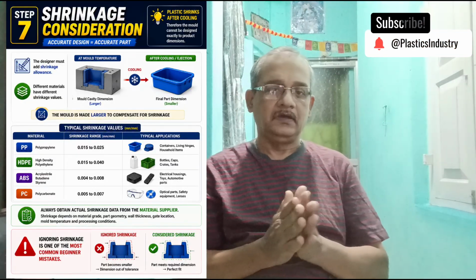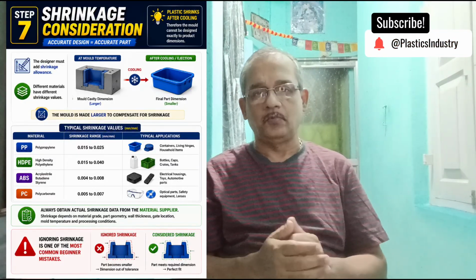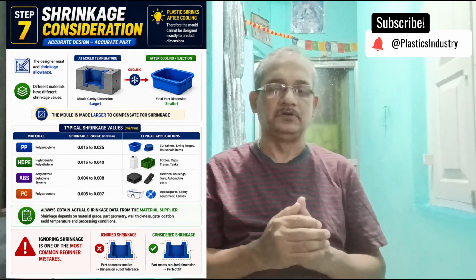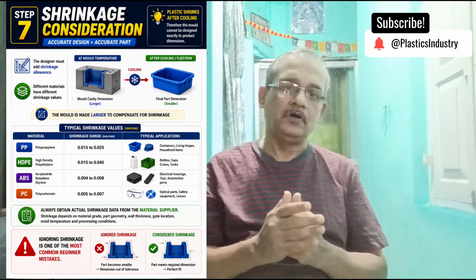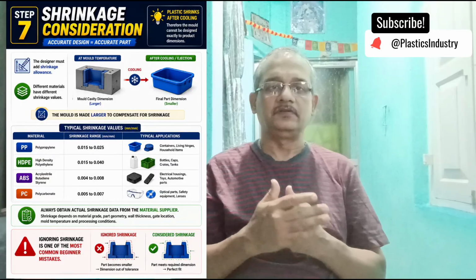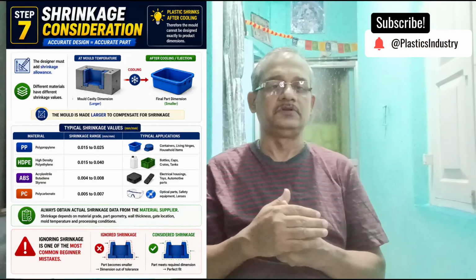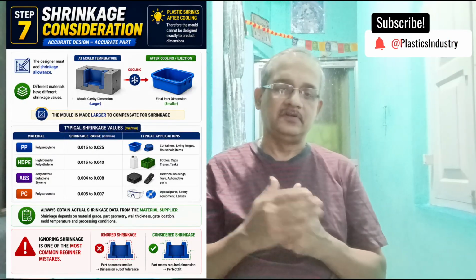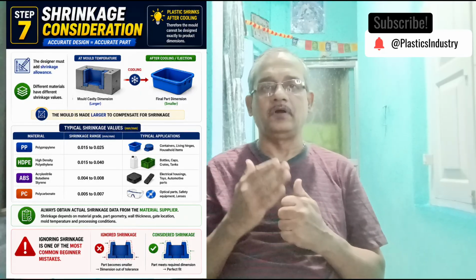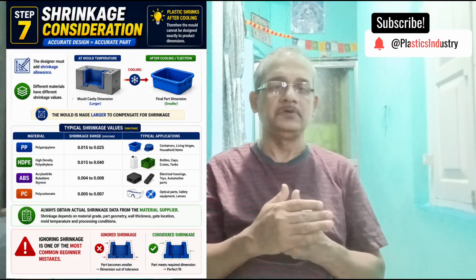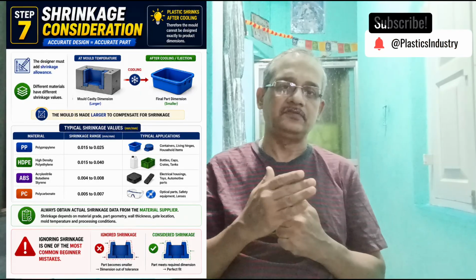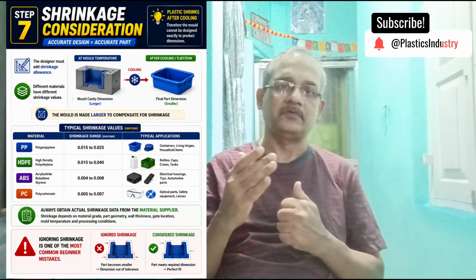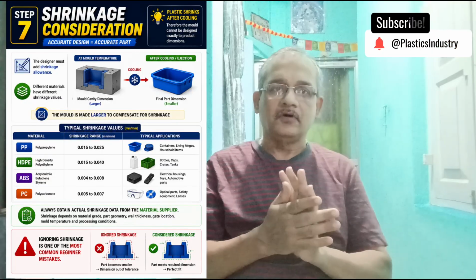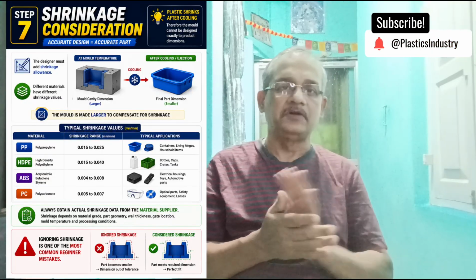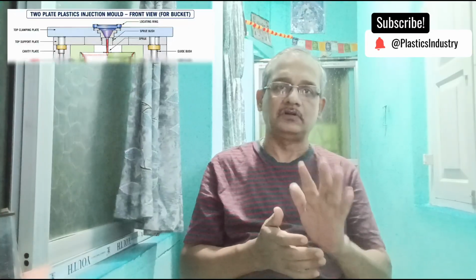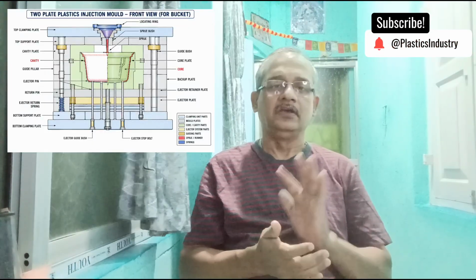Examples: PP 0.015 to 0.025 millimeter per millimeter, HDPE 0.015 to 0.040 millimeter per millimeter, ABS 0.004 to 0.008 millimeter per millimeter, polycarbonate 0.005 to 0.007 millimeter per millimeter. Always obtain actual shrinkage data from the material supplier. Ignoring shrinkage is one of the most common beginner mistakes.